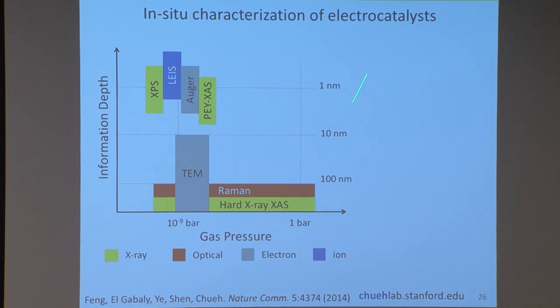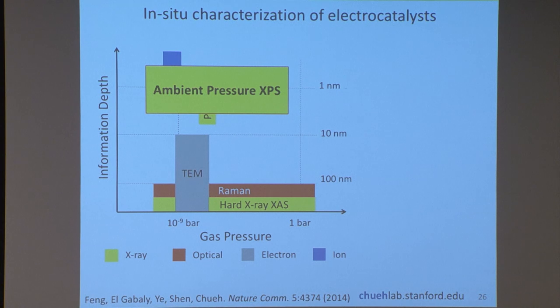And there are many techniques here, I won't get into details, but they occupy either very surface sensitive by vacuum, or less surface sensitive, but you can go to the high pressure. What you really want is the top corner here, in which you're very sensitive to the active site, but also can operate at high pressure. And that's what we've been developing in the past few years, is developing spectroscopy techniques using synchrotron radiation so we can directly probe the active site. So this is actually a really important technological breakthrough in characterization that allows us to watch these reactions as they happen and to monitor the behavior of defects.